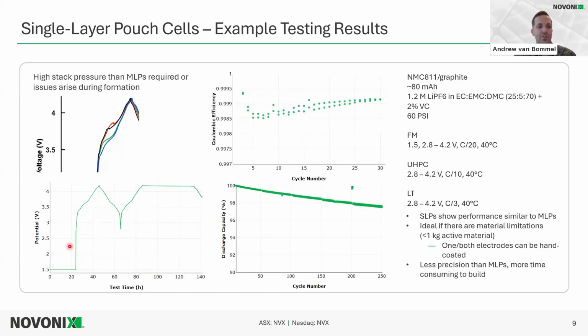So these single layer pouches, there's two formation curves over here. So there's excellent formation for those when it did have the higher stack pressure. And then we did UHPC cycling on that, so using NOVONIX UHPC. And there are some differences between one and the other cell, but we do see this sometimes as well with multi-layer pouches. There might be more differences with single layer pouches because we only have that single layer and there's less evening out of slight differences in mass loading. But we're getting above 99.9% Coulombic efficiency, which is higher than some commercial cells. So here's an excellent single layer pouch.